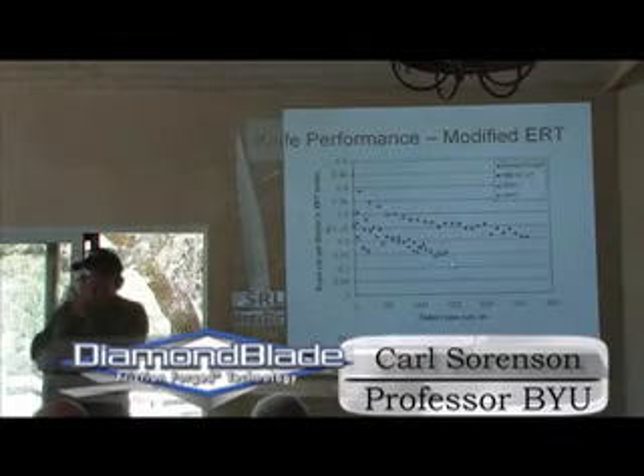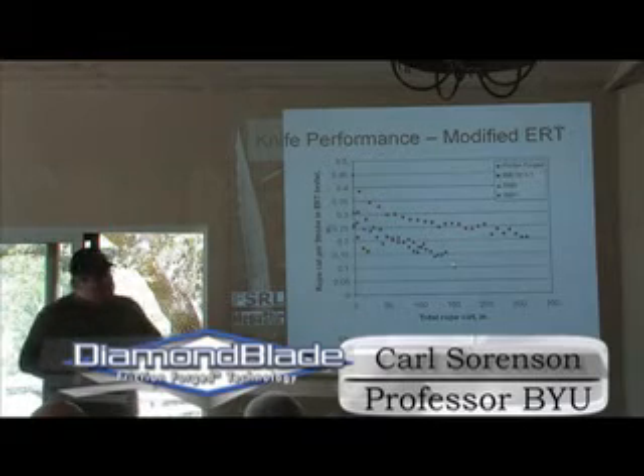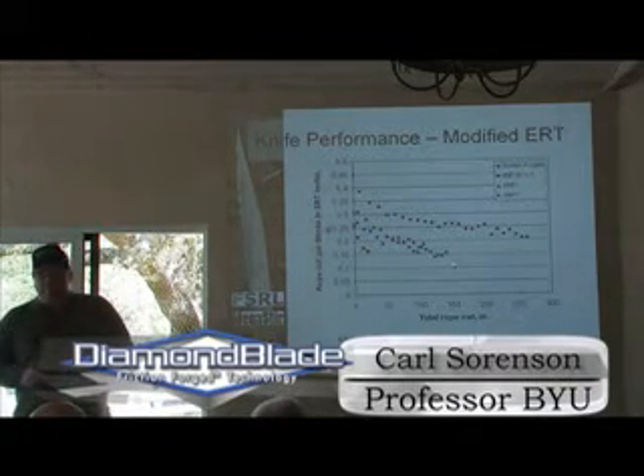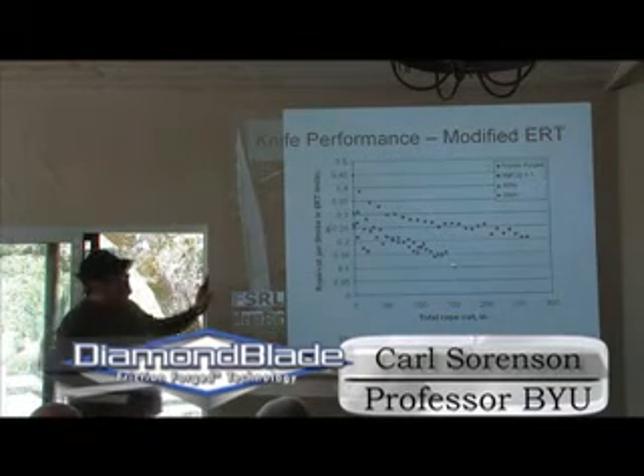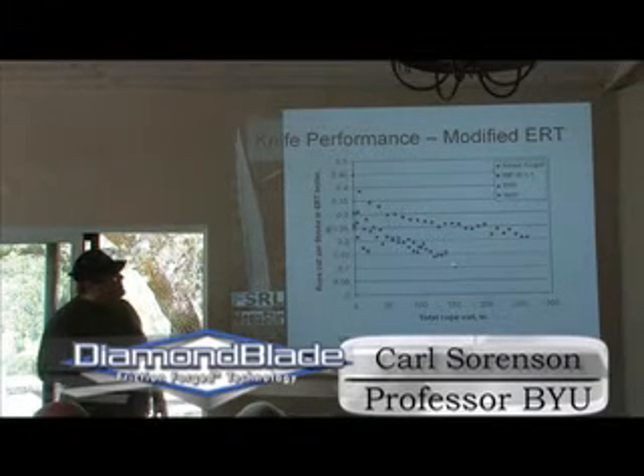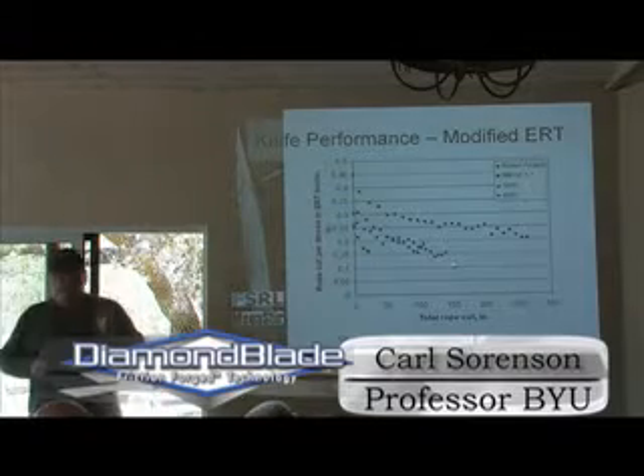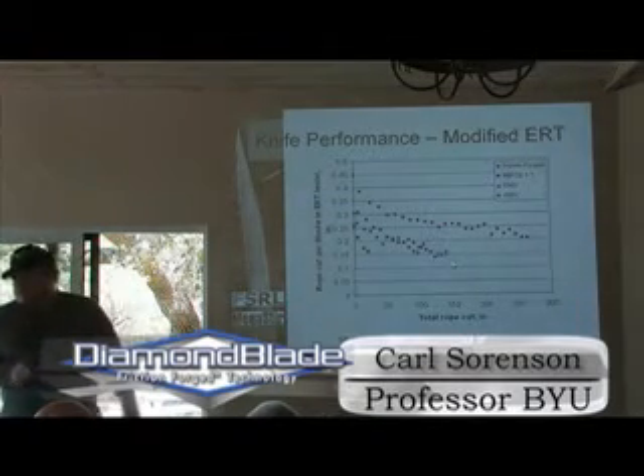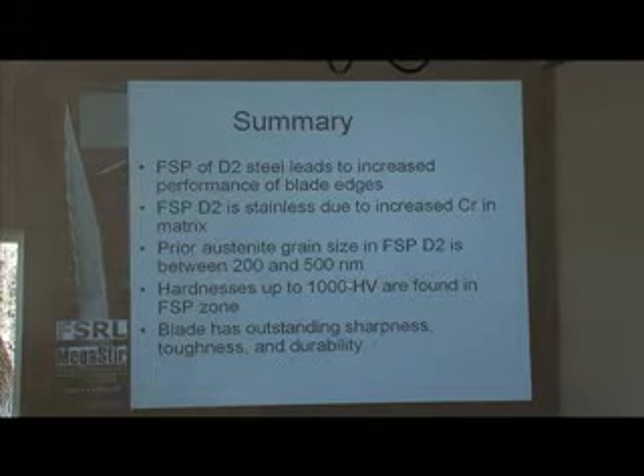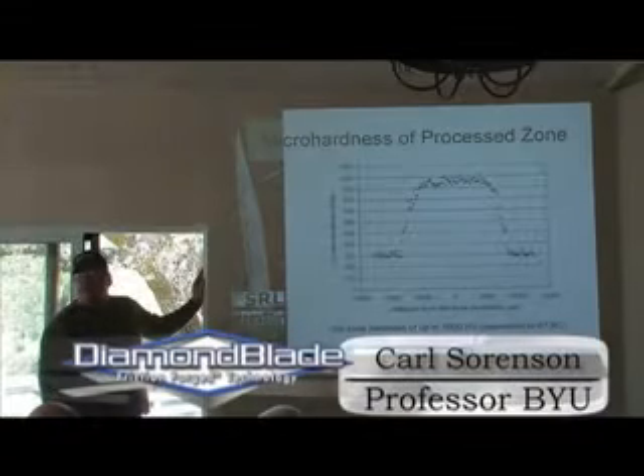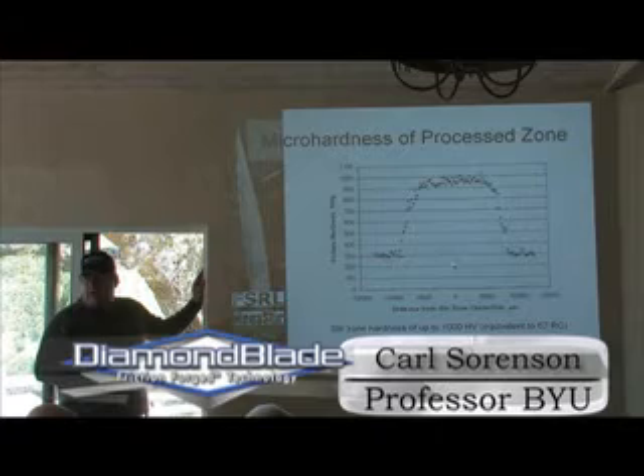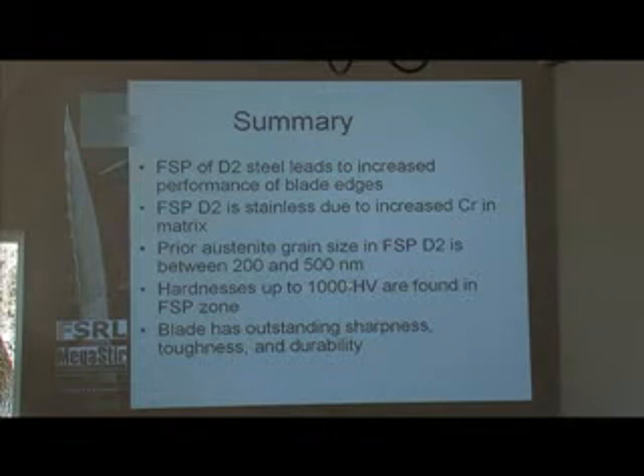So we've got 3 premium knife alloys, D2, S30V, S90V, compared to the ultra premium knife alloy, friction forged D2. The friction forged is 50% sharper than the best of the others, the S30V. So we have a sharper initial blade, and we have a much longer lasting blade. The grain size is between 200 and 500 nanometers, 1/10 of the grain size in traditionally processed steels. We're off the chart on grain size, and we're off the chart on hardness. We have hardnesses up to 1,000 Vickers, and we have outstanding sharpness, toughness, and durability in the edge as a result of this new material that's created in the friction forged region of the blade.